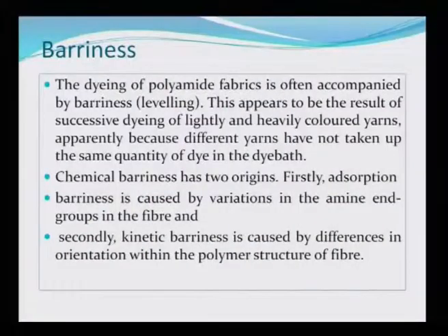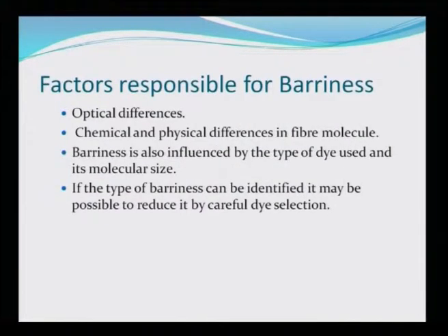Because this is not like chemical dyeing, where there is a direct covalent or coordinate bond formation between the metal and the fiber, it is very different. Because of this difference, there is only physical adsorption, bringing the dye aggregate closer to the fabric as far as possible, and the protonation of the fabric and so on causes the dye to come closer. Factors responsible for barriness: optical differences, chemical and physical differences in the fiber molecule. Barriness is also influenced by the type of dye used and its molecular structure or molecular size. If the type of barriness can be identified, it may be possible to reduce it by careful dye selection.